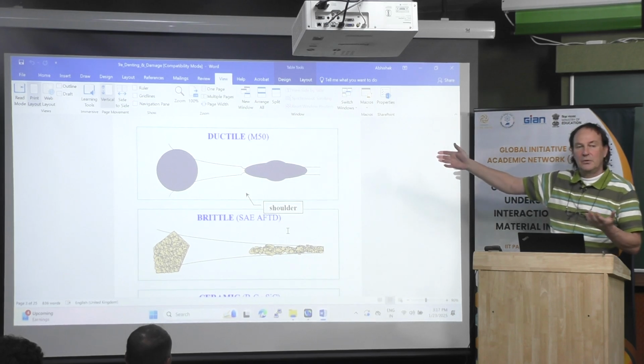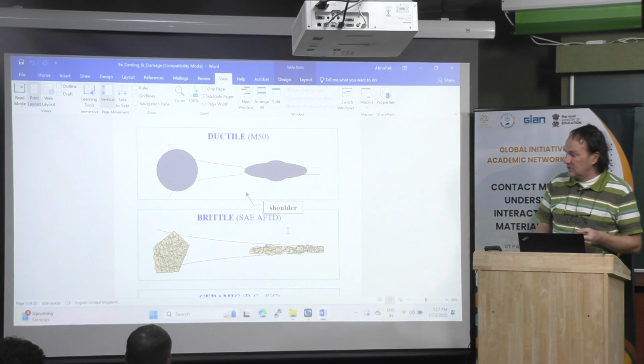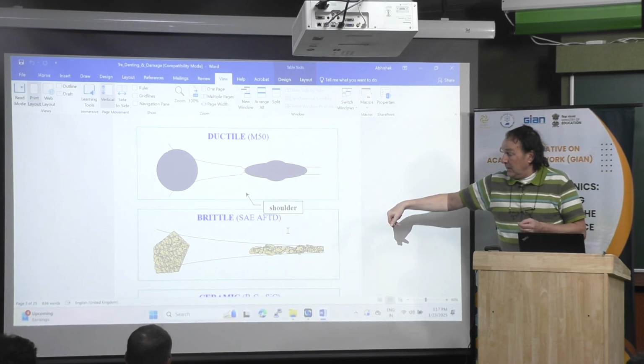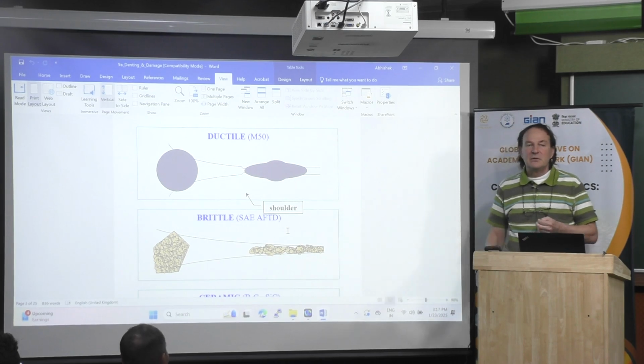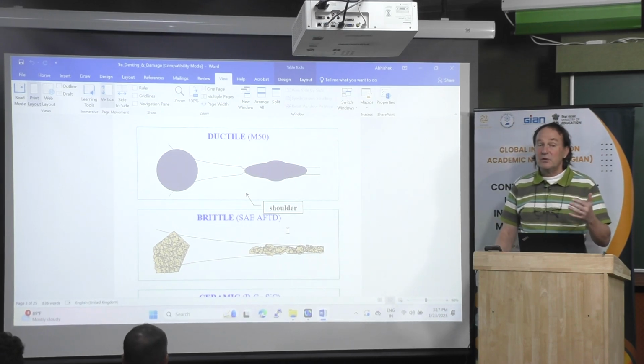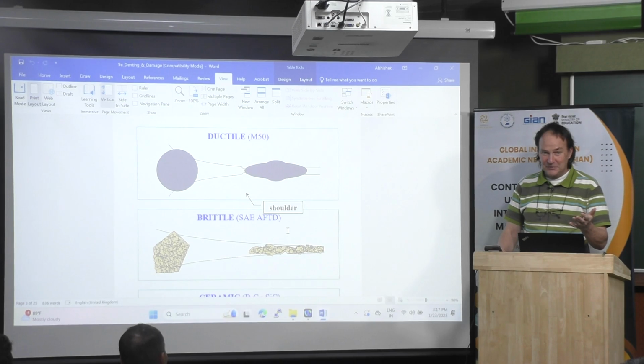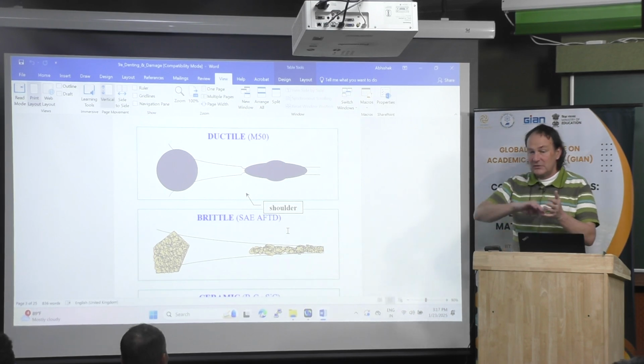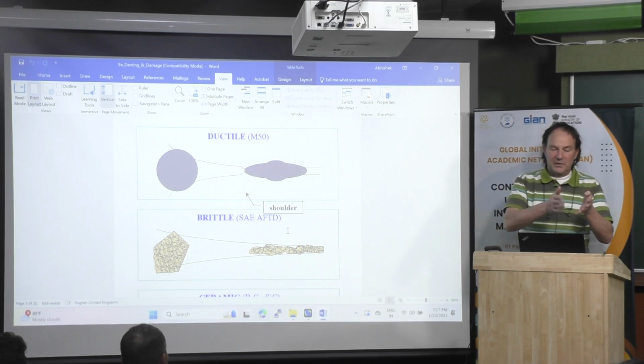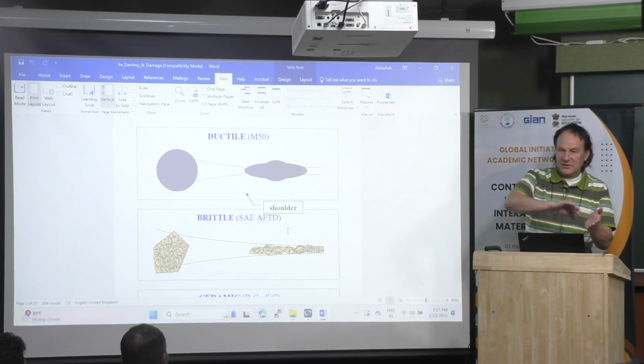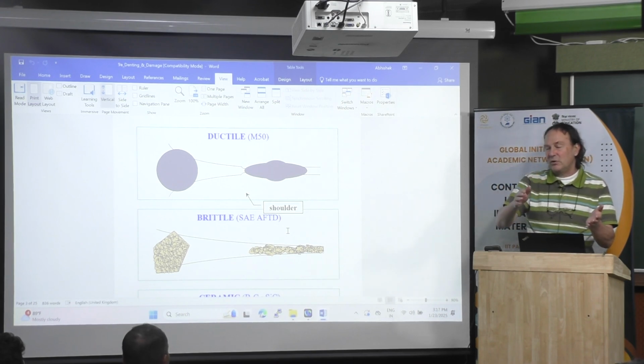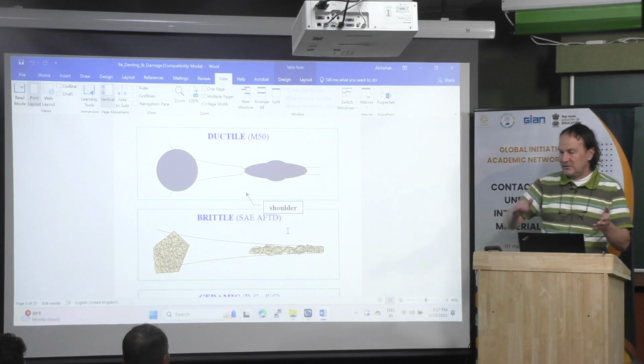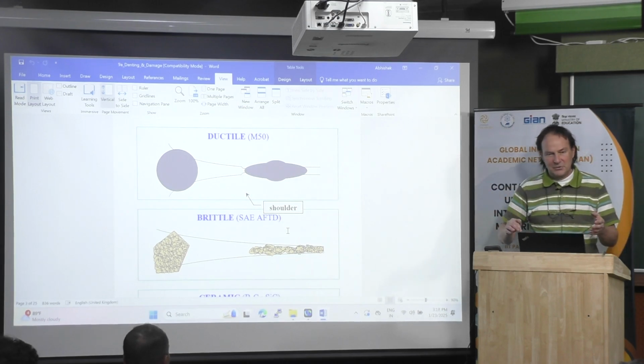Then this is a real schematic view, but coming from experiments. When you have brittle materials, AFTD, in fact it's a sand. It's a silicon sand coming from some desert in the US. And they sell the sand, it's very expensive, very, very expensive. A kilogram should be a few $100s. Because it is calibrated and there is a norm, you have such number of particles smaller than 2 micrometers, and you have a Gaussian distribution, and then above 100 micrometers, there is almost no particles. And there is some type of, not Gaussian, but a distribution of particles.